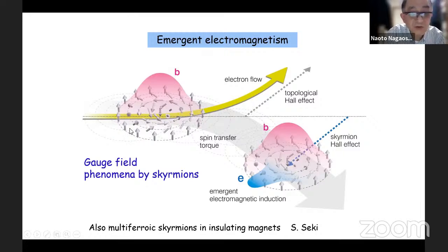So for example, if we have a skyrmion here, then the conduction electron will be deflected because of the emergent magnetic field, small b. So this is called a topological Hall effect. And the spin transfer effect drives the skyrmion motion, but in some transverse way, namely the counteraction of this topological Hall effect leads to the skyrmion Hall effect, which goes this way.